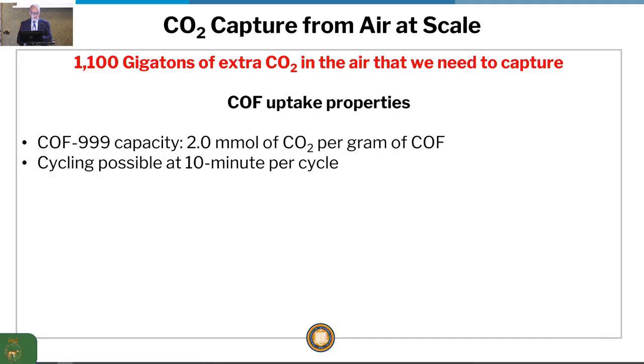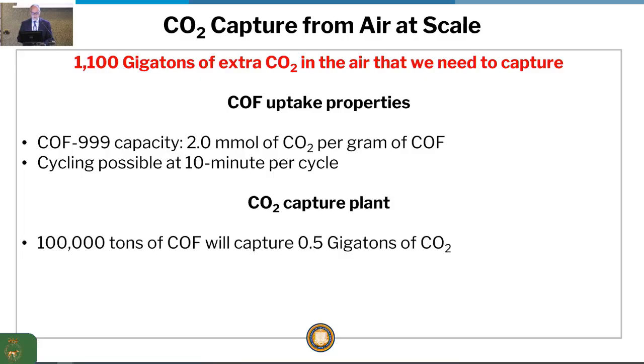And the cycling can be done very fast because the COF framework, as I showed in the movie, is quite open, so the pores never get clogged. It's really a scaffolding, and things can diffuse in and out very quickly. So with these parameters, I need 100,000 tons of COF to capture half a gigaton of CO2 every year.